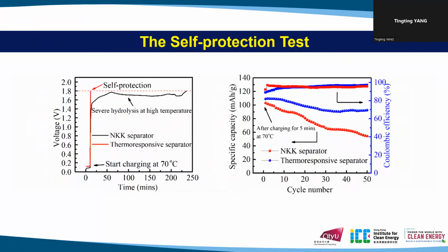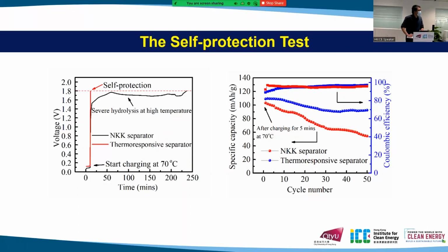And this is a self-protection test, because we know that the battery could stop working at high temperature, but we don't know how well the self-protection performs. So we operate the battery at 70 degrees for 5 minutes, and we find that nothing changed for the one with the thermal responsive separator, but for the normal one, there is very serious hydrolysis at high temperature. Then we cool down the battery to room temperature, and we find that the capacity decays much faster with the normal separator than with the thermal responsive separator, which proves that this protection works.